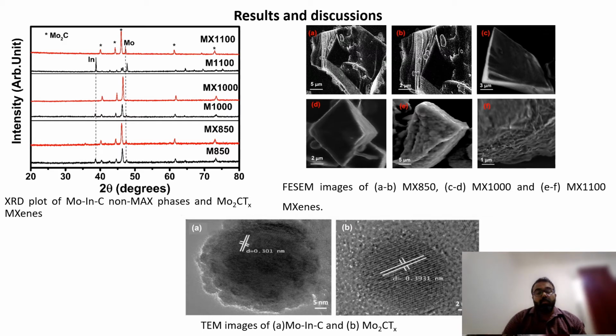Also, we studied the morphology of the synthesized MXenes, and all the samples gave layered two-dimensional morphologies, which confirm the formation of MXenes. Also, we have done transmission electron microscopy studies, and we confirm that the interplanar spacing between the layers is increased when a MAX phase is transformed to MXenes. This is because of the selective etching of a layer, creating a vacant space between the planes, which creates an increase in the interplanar space. So this increase in the interplanar space also confirms the formation of MXenes.